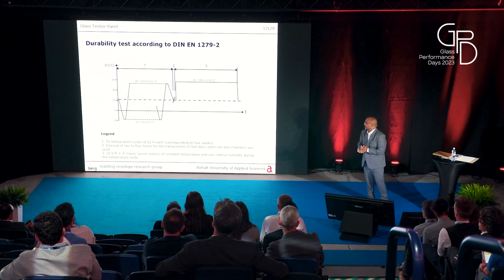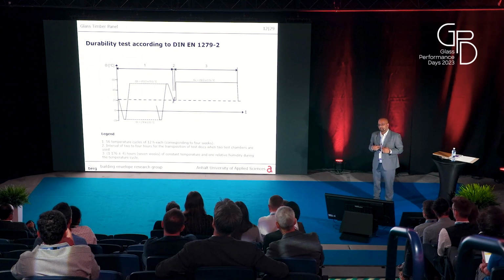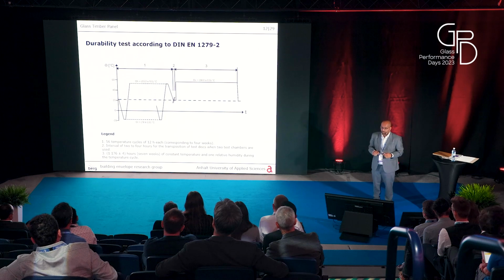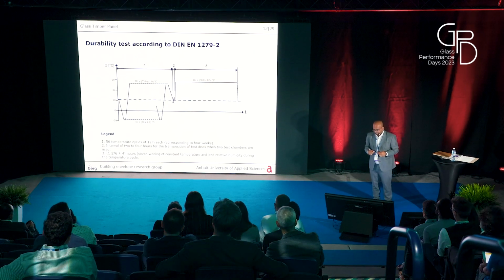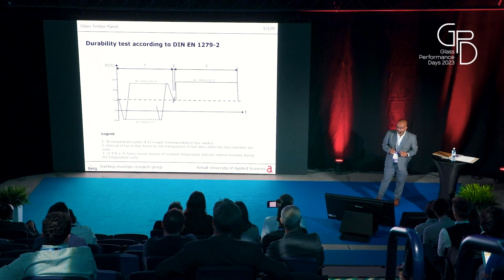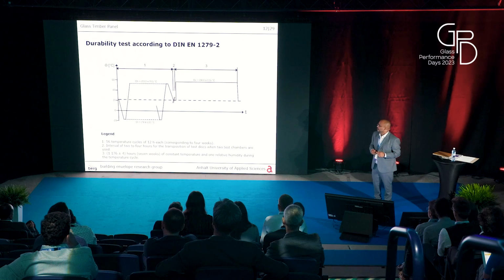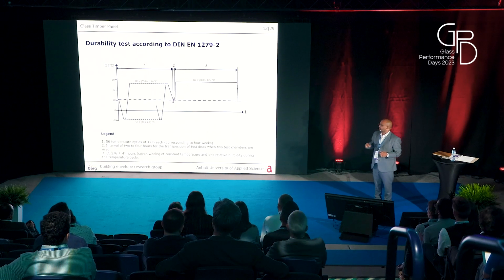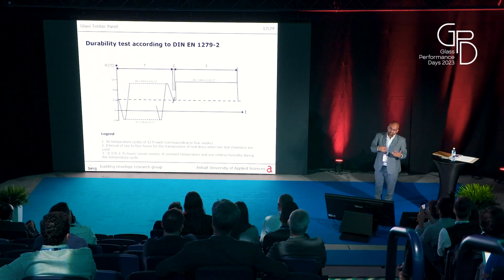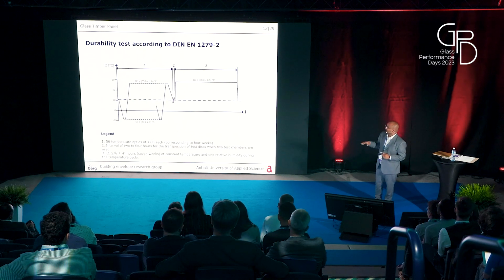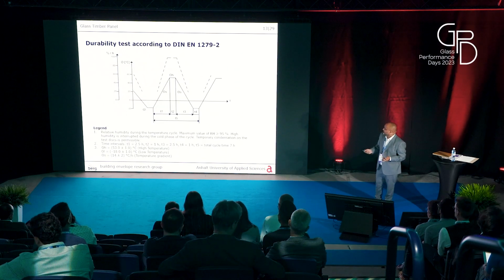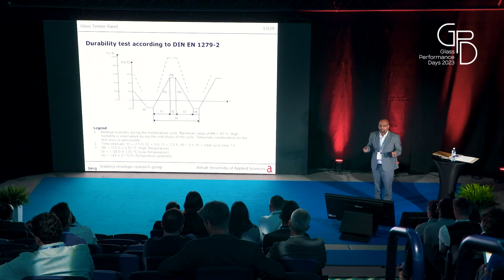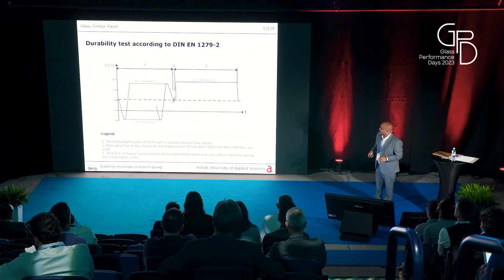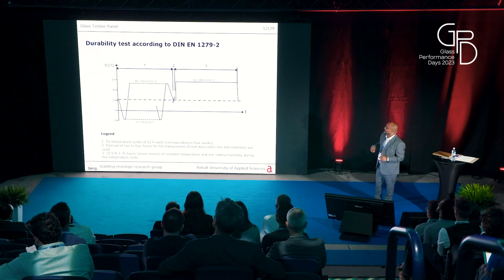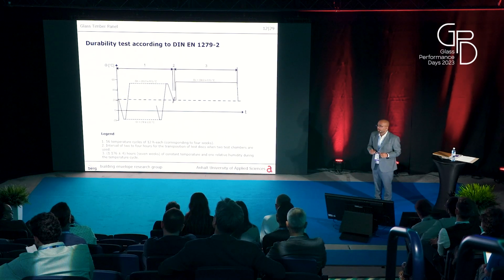And then we checked some durability tests. Since there are no defined DIN standards for this, we used the DIN which was used for lamination, for testing the moisture penetration test for laminating glass. It's done in 2 phases. In the first phase, there's a cyclic test of changing the temperature from minus 18 to 53 degrees, trying to control a constant moisture of more than 95%. And this was done for 1.5 months. That's 56 cycles, and then keeping the whole sample at constant moisture of 100% at a temperature of 58 degrees.